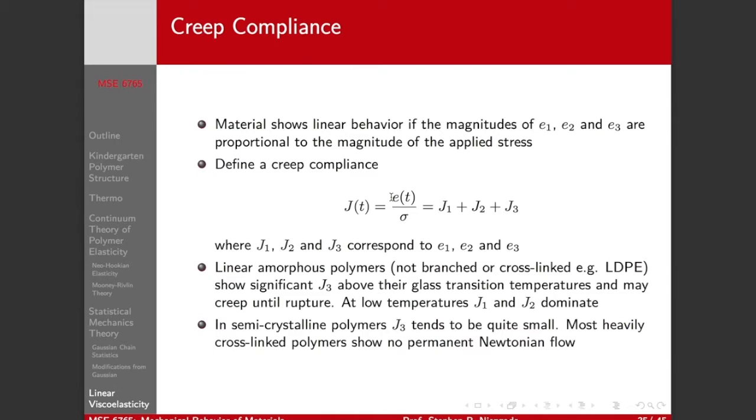It's a linear behavior if the magnitudes of E1, E2, and E3 are all proportional to the magnitude of the applied stress. And so what this creep compliance is, it's the strain as a function of time divided by the stress. So this creep compliance is a time-dependent function.